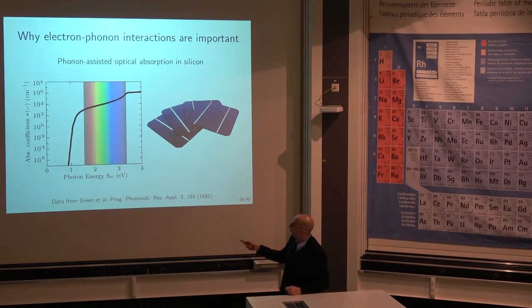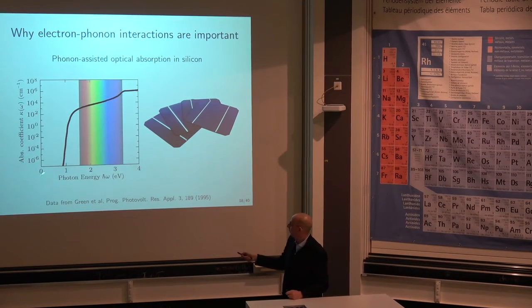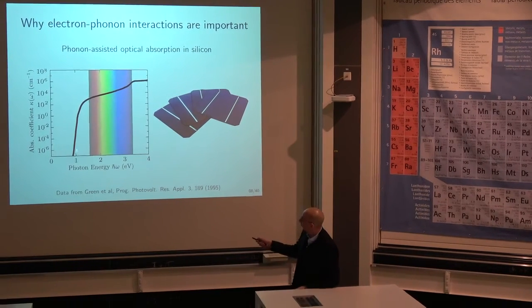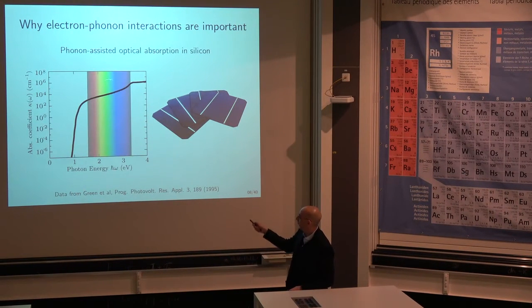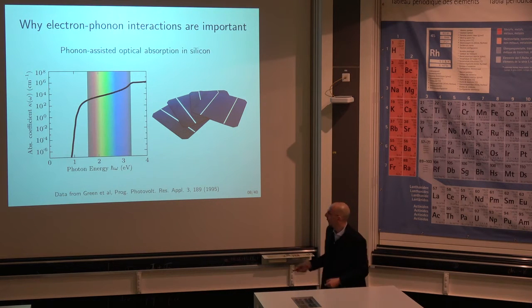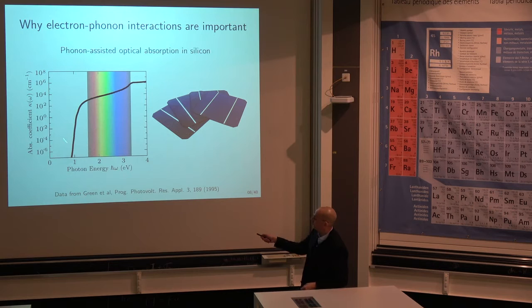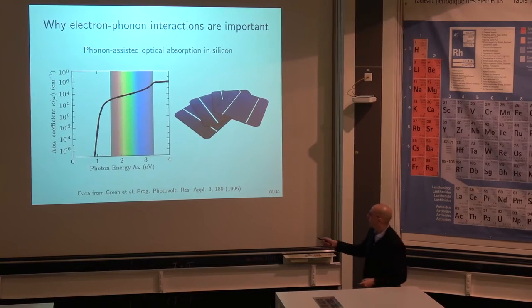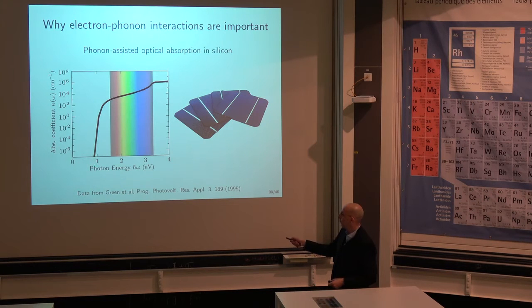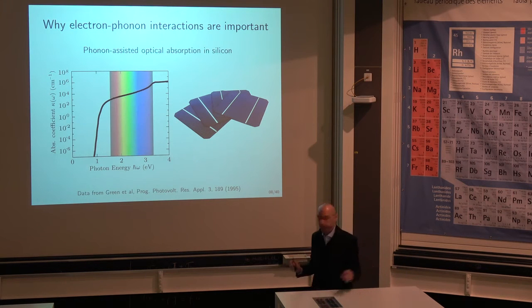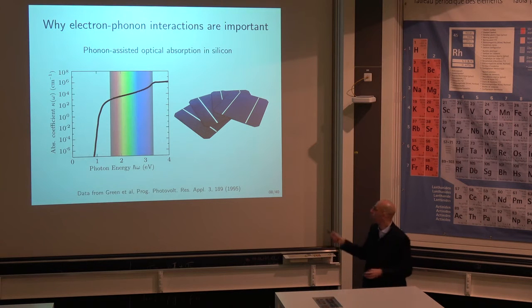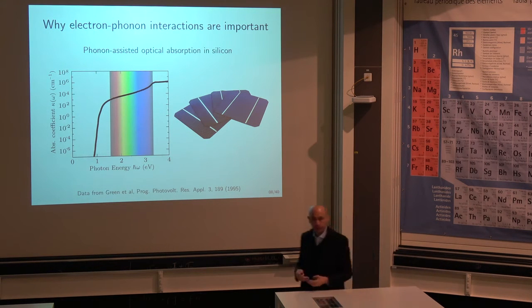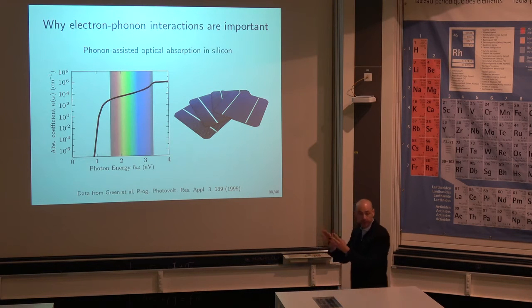What you're looking at is the absorption coefficient of light of silicon as a function of photon energy. This is the measured absorption coefficient, this line. And I overlay the visible spectrum, visible light. Solar light is pretty much in this range plus the infrared, okay? Now, what you probably know is that silicon has an indirect bandgap of 1.1 electron volts and a direct bandgap of about 3.3 electron volts, okay? So if there were no electron-phonon interactions, all this absorption from here to here would not exist. It would be essentially 0, okay? That means that if there were no electron-phonon interactions around, one could not make this kind of objects, okay? So silicon is an indirect gap semiconductor, and it absorbs light in the right region precisely because there are